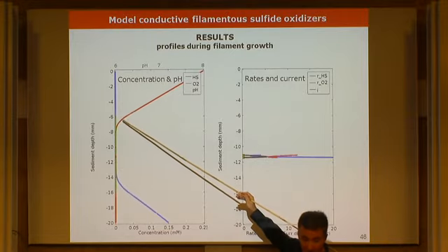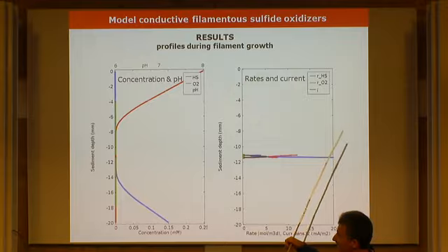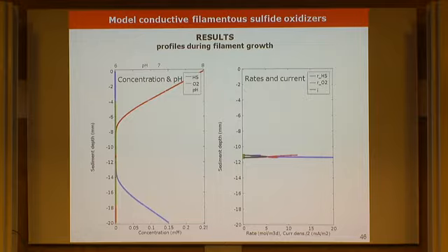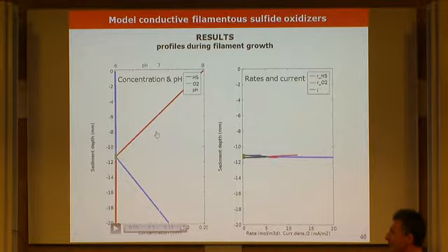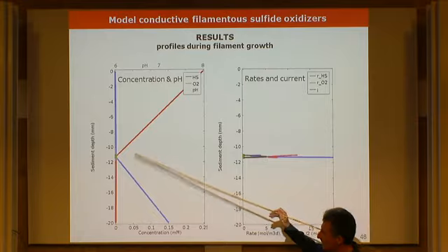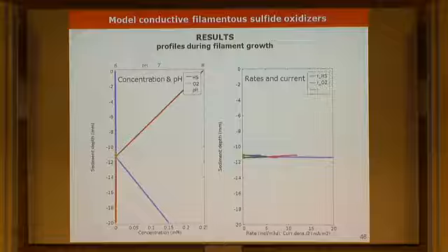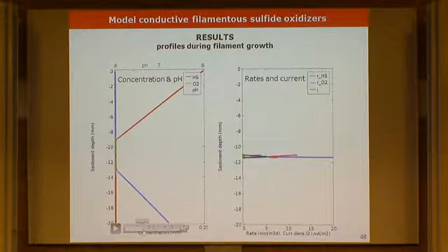The green part here is the filament, which grows. So if I can play this again, you see how, okay. This is the initial situation, trivial sulfide oxidizers. They just grow where oxygen and sulfide meet. And then you see here, this part, now the two zones separate. Sulfide is here, quickly consumed, electrons transferred here. At the end, there is conduction limitation. You see that even if the filament has grown like this, the reaction takes place still here.